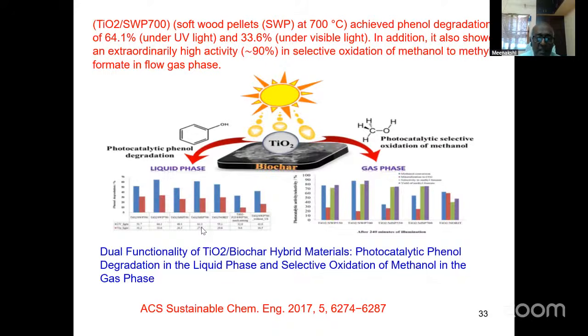And another one is biochar from softwood pellets. They prepared the biochar from the softwood pellets with TiO2, the TiO2 SWP 700, and this is used for degradation of phenol. It has a dual function. In the liquid phase, it is used for the degradation of phenol. In the gas phase, it is used for the conversion of methanol into methyl formate.